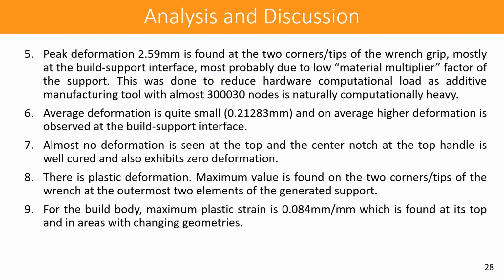The average deformation is quite small, 0.21283, and on average, the higher deformation is observed at the build support interface. Almost no deformation is seen at the top, and the center notch of the top handle is well cured and also exhibits zero deformation. There is plastic deformation.